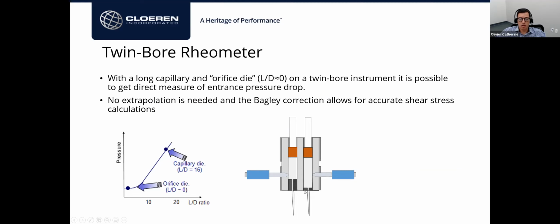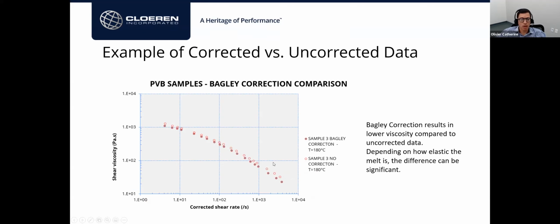And specifically, they have an L over D die close to zero. Here we call it orifice die or zero length die. It is in fact 0.25 millimeter, if I remember. But basically with this on the right side of the rheometer, you are measuring the entrance pressure and you remove it directly from the left side measurement, and you have a 2-point Bagley correction, which is very accurate and very, very efficient. So that's what we do all the time.